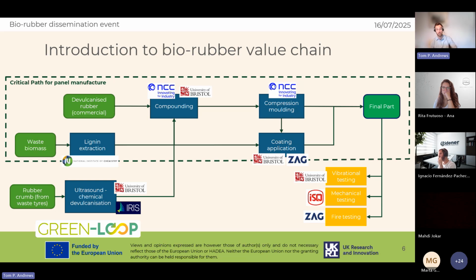That then comes to us at the NCC. We compression mold it into panels, and we've scaled up all the way up to about 0.5 meter by 0.5 meter panels. Sometimes that's the final part. Sometimes there's a coating application either at Bristol or ZAG. And then those final parts go through testing, essentially. So vibrational testing at the University of Bristol, mechanical testing at ISQ in Portugal, and fire testing at ZAG in Slovenia. So that's the critical path.